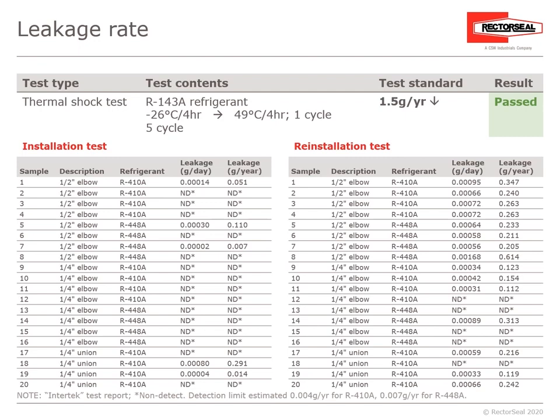A test standard which is no more than 1.5 grams per year as a pass condition. On the left table, you'll see the installation test, 20 samples, half-inch elbow, quarter-inch elbow, and quarter-inch union. On the far right column of that table, again, the test standard is to be less than 1.5 grams per year, and you can see on all those samples, it is significantly less than that.